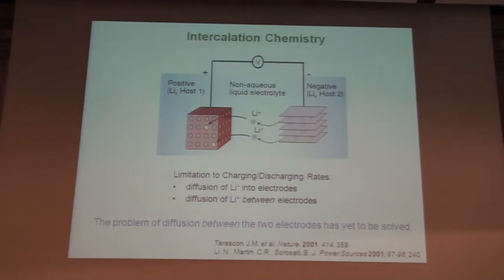So we've been thinking about ways to try to improve on this battery while still maintaining basic lithium-ion battery chemistry. So I want to explain a little bit about how your battery actually works so you can see the approach that we've taken. In a typical battery, you have two electrodes, your cathode or your positive electrode and your anode, the negative electrode. In your cell phones, you have a cathode that's composed probably of lithium cobalt oxide or lithium iron phosphate. It has transition metal ions in it that are redox active. On the other side, you have graphite, and this is the side that lithium intercalates into when you charge your battery. So the lithium ions are stored between the layers of the graphite.